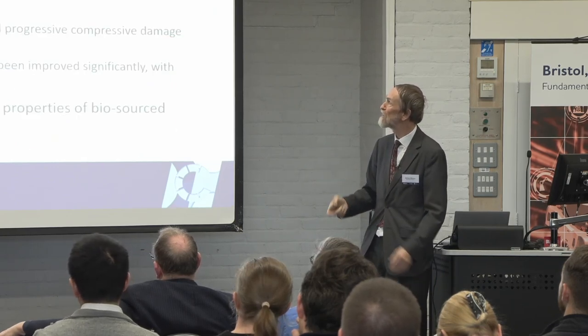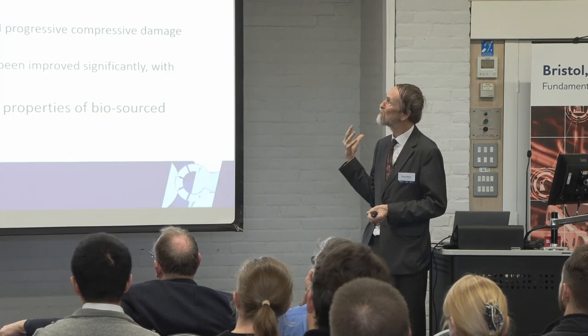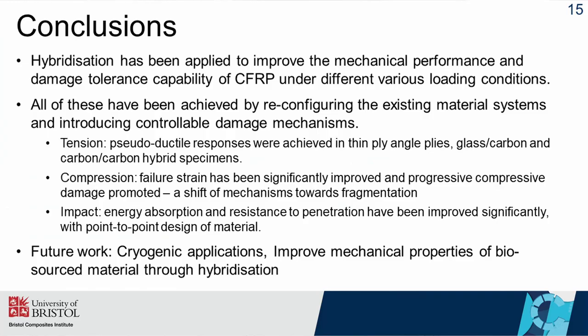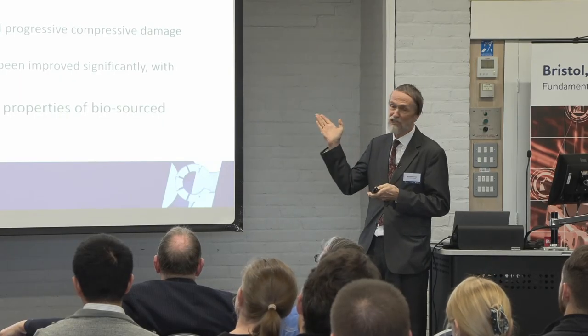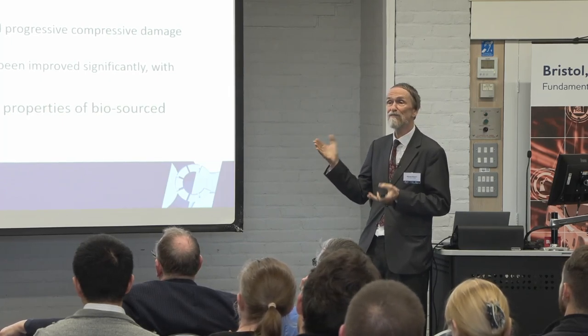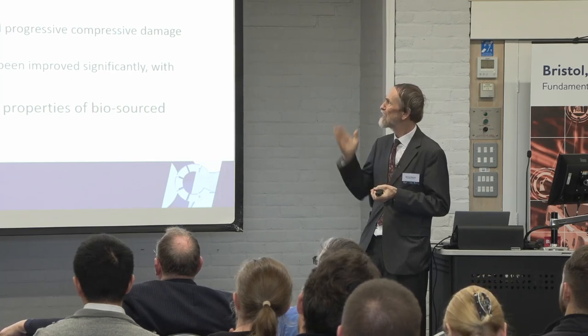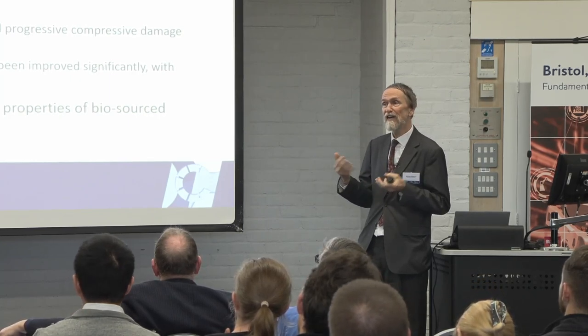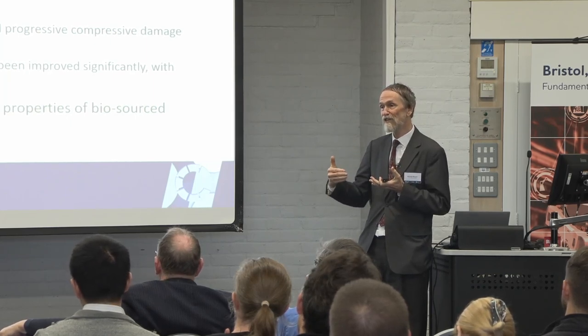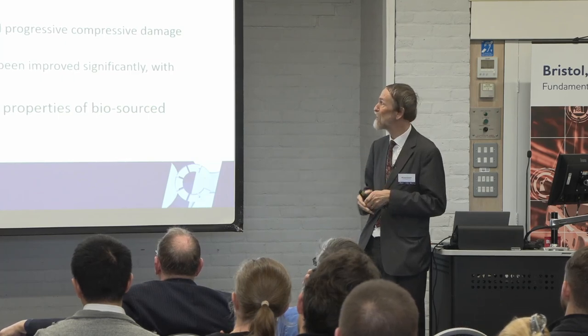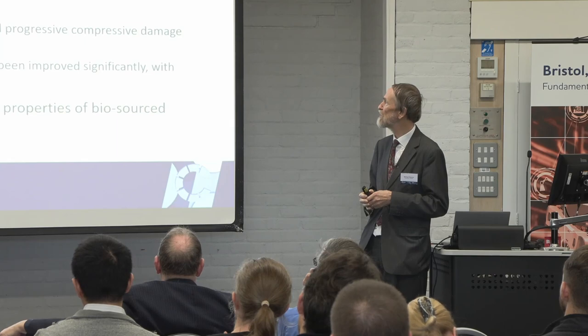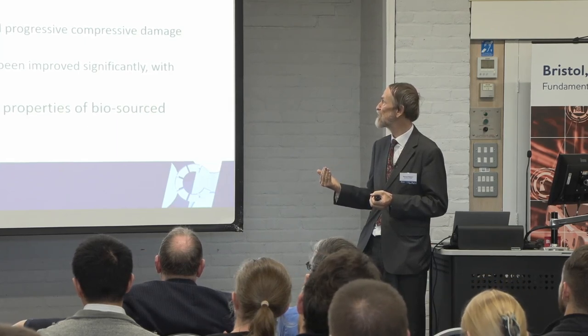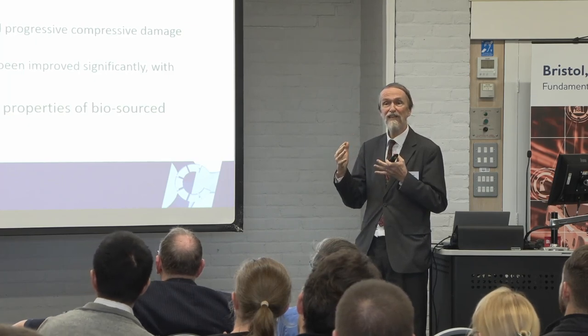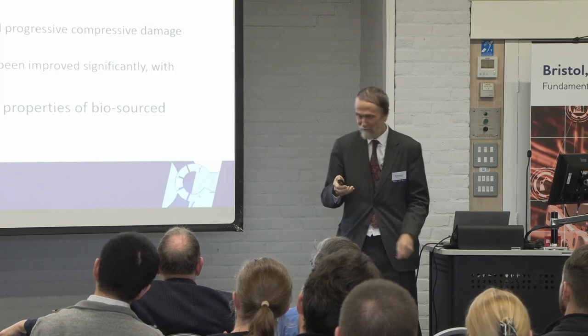So this is quite an interesting possibility of using these thin ply materials and perhaps bespoke architectures to deal with these cryogenic applications. So in conclusion then, I've shown that we've applied hybridization to improve the mechanical performance in different conditions. And we've done that by taking existing materials and then applying them in different ways to try to control the damage and the failure mechanisms. So in tension, we get pseudoductility by different mechanisms, by combining different materials to get fragmentation. In compression, we've also been able to achieve fragmentation and shown a transition in failure from a catastrophic to a more gradual failure and also an increase in the failure strain. And then in impact, energy absorption, we've been able to significantly improve the penetration resistance by designing the material for the particular case to get the best properties. With that, I'll finish. Thank you very much.